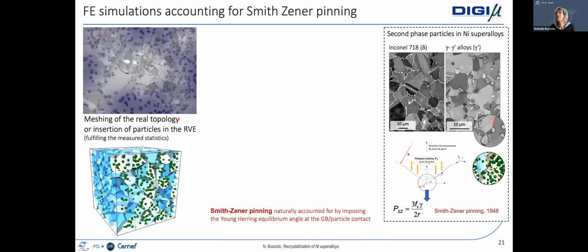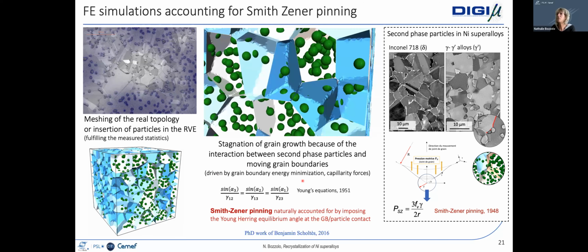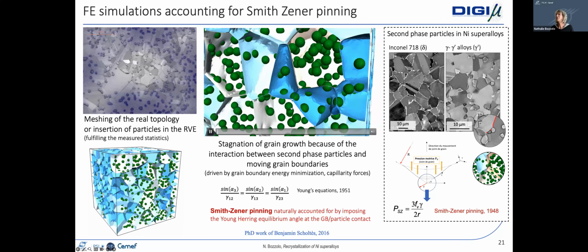So we have to describe the second phase particles. For this, we can either use an experimental image and immerse it in a finite element mesh. This is what you can see on top here. Or we can generate a statistical distribution of second phase particles. This is what is done here in this 3D example. Then we can run a grain growth simulation, for example. So here you have grain boundaries, you have second phase particles, and if I can click, I can show you this. So this is the simulation of grain growth.